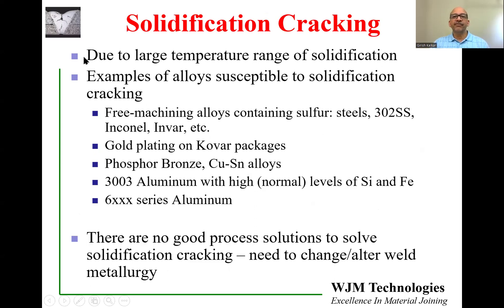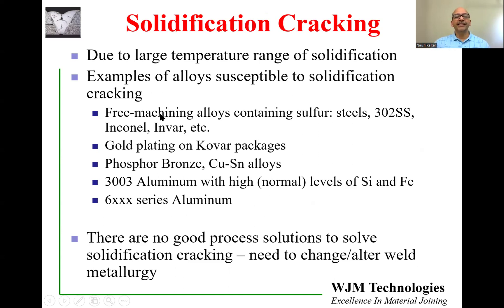The main reason for solidification cracking is a large temperature range of solidification — the primary alloy solidifies at a high temperature while grain boundary impurities solidify at a much lower temperature. The main example we discussed is steels, and it commonly occurs in free-machining alloys with up to 0.3% sulfur. This applies to steels, stainless steels, Inconels, and Invar — there are many examples of such failures.